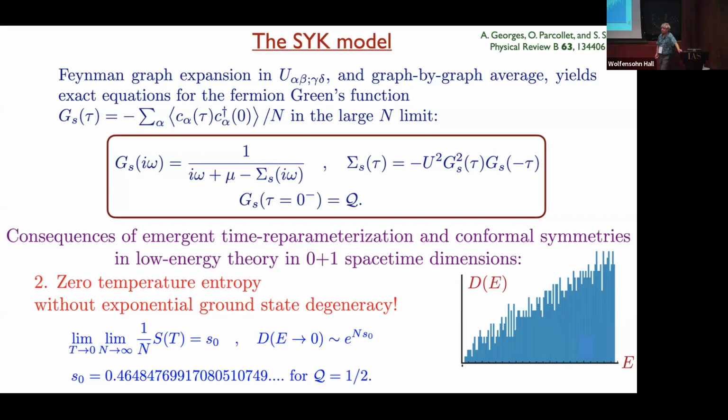Question. The experiment, strange metal seems to be explained at kind of high temperatures. Why is the model targeting to understand zero temperature? Well, okay. So here there's only one scale, which is U, and U or J. J is about 2,000 Kelvin, and U is 10,000 Kelvin or something in cuprates. And the experiments we're talking about are at most 200 Kelvin. So even what's the high temperature region of the phase diagram is really quite low.